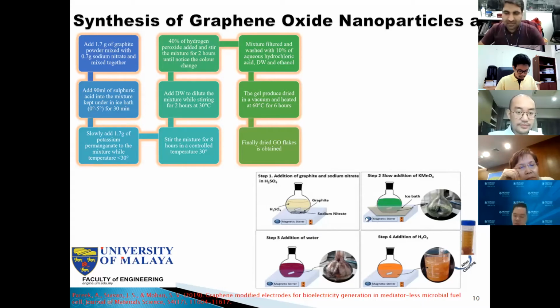So here you can see the schematic diagram of the synthesis of graphene oxide. We have the graphite flakes, then we use sulfuric acid and put it in the ice bath, and we add the potassium permanganate to control the reaction. Finally, we add water, then finally the hydrogen peroxide. And finally, we got it in such a way.